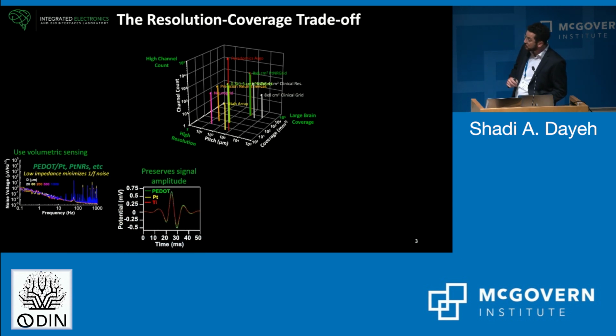Now, the electrode size also has implications on the amplitude of the signals, not only the noise. Here we're showing this for 3 contact materials placed within 50 microns from each other: PEDOT, and 1 order of magnitude higher, platinum, and then another order of magnitude higher, titanium. This is in terms of impedance. And as we get to the titanium electrode, the measured potentials for the same evoked activity, the amplitude is reduced by about 10% or so. This is because the impedance of the electrode becomes a fraction of the input impedance of the amplifier.